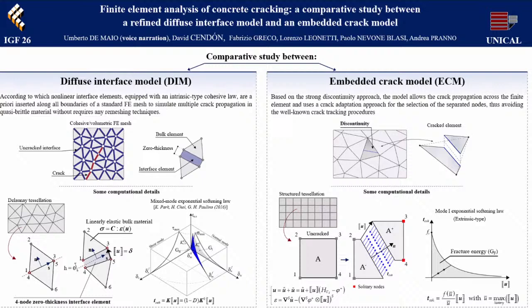So this work is focused on a comparative study between two numerical fracture models. On the one end, the diffuse interface model is based on an inter-element cohesive approach, according to which interface elements are inserted a priori in a standard finite element mesh to simulate crack propagation. The zero thickness cohesive elements are governed by a mixed mode exponential softening law.